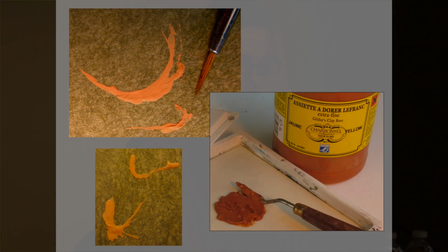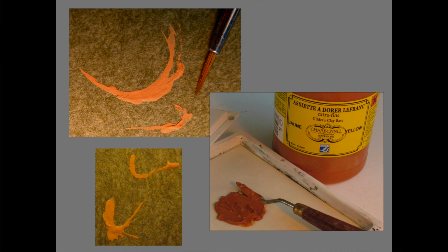Then I experimented with a range of fine conventional sable brushes using a clay bowl manufactured for gilding frames. At the necessary consistency to make a three-dimensional line, the clay bowl did not flow or easily transfer from the brush to the paint substrate. And when diluted to make it more fluid, the line lacked the unique relief quality that we were looking for. Also, it was not possible to create a line with a sharp turn in it. The brush hair would flick out when making a turn in the line, leaving a muddy mess, as you can see here.